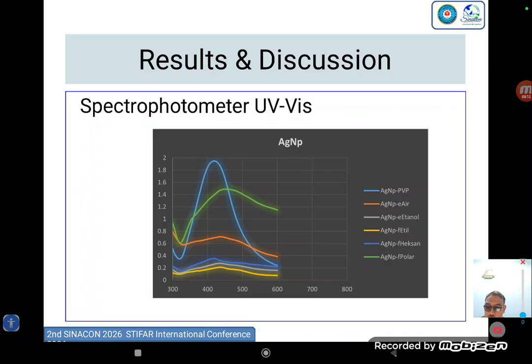The synthesized nanoparticles were characterized using UV spectrophotometer in the wavelength range of 200 to 800 nanometers to confirm the formation of silver nanoparticles. The UV spectrum exhibits distinct peaks at the 400 nanometer region. The peak at 400 nanometers is the characteristic peak of the silver nanoparticle.